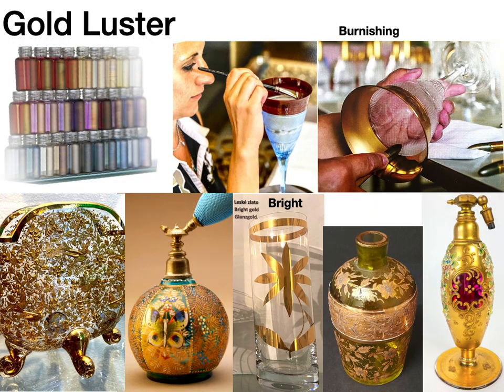Gold luster is not an enamel, it's metal oxide. Enamels are glass. Gold luster has to be fired differently from colored enamels. It's often fired in an electric kiln, which keeps it out of contact with gas fumes. It's fired at a lower temperature in a reduction atmosphere, which means a lack of oxygen. After the gold is fired, it has to be cleaned or burnished with an agate or other material if you want it to be shiny.